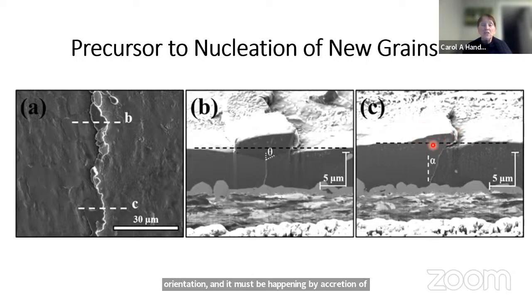So we do EBSD here, and at other positions along the boundaries, this is the original boundary, and we see the formation of a new grain boundary by the accumulation of those dislocations. And then once the boundary actually forms, then the whisker can begin to grow. It grows on both sides, not just tilting up.